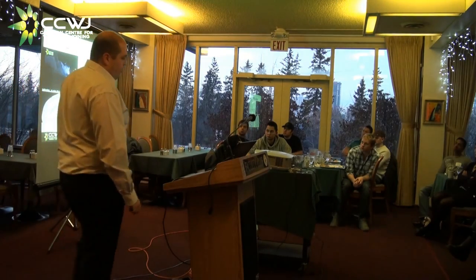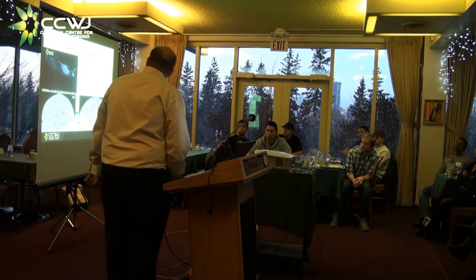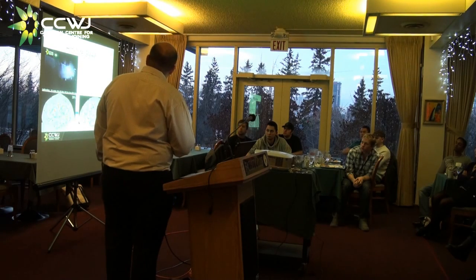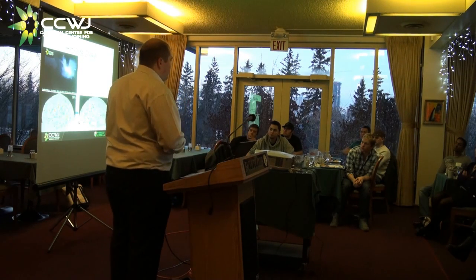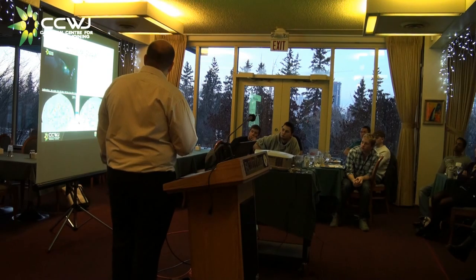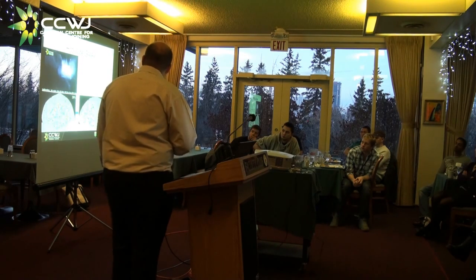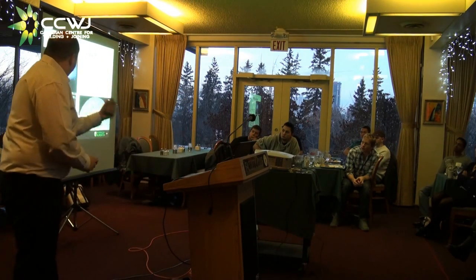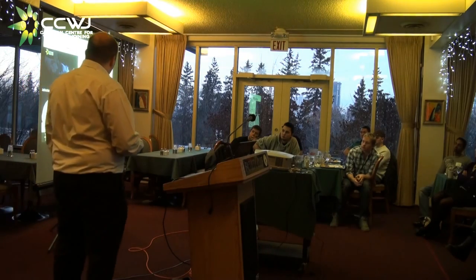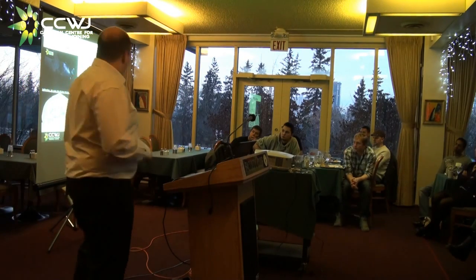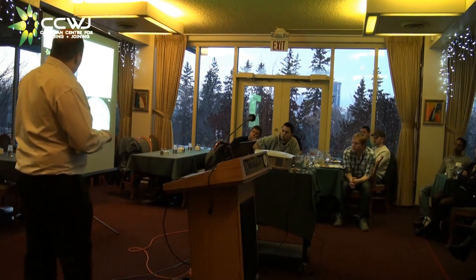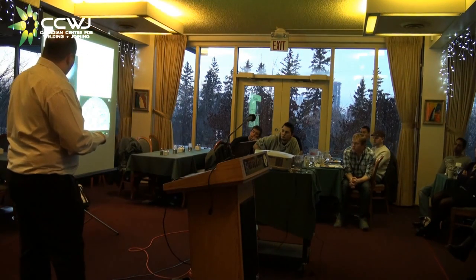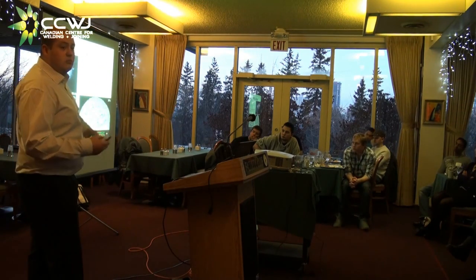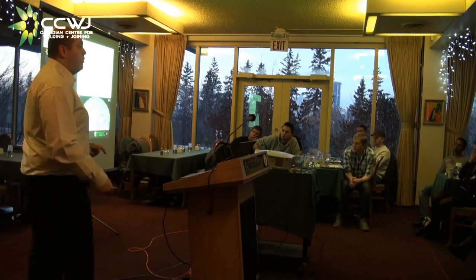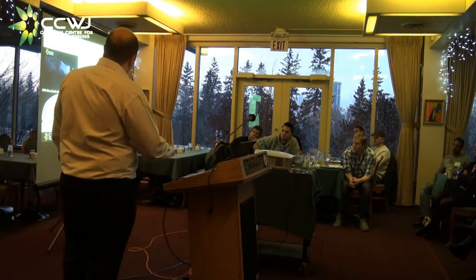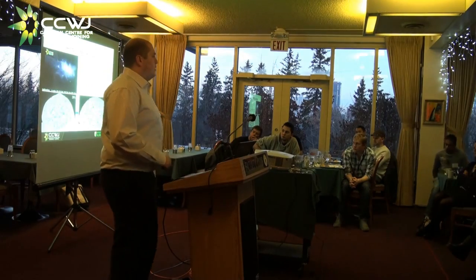So here's a high-speed video of the hot wire. You can kind of see the hot wire here. It's glowing. It's actually surprisingly difficult to high-speed image a bright welding arc and a glowing metal rod, but we can do it. Basically, with the hot wire MIG process, we can take an overlay fraction, a standard MIG overlay with 28%. It's not bad considering our consumable only started with 35%. And with the hot wire, bring it up to 36%.